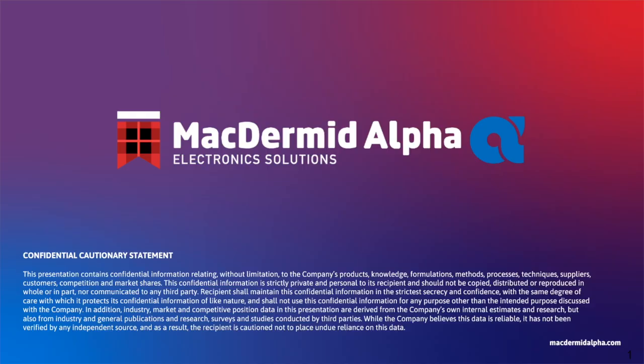In terms of how we assess EBO, it's typically a visual test where you dispense a pattern, and essentially EBO can happen at two instances. One is instantly as a reaction to the dispensed material on a surface. So depending on the surface characteristics and surface energy that you're dispensing a material on, and how is the interaction of your chemistry to that surface, in some cases you can instantly start to see material leaching out or showing a bleed out. And you can capture that with high resolution microscope images.